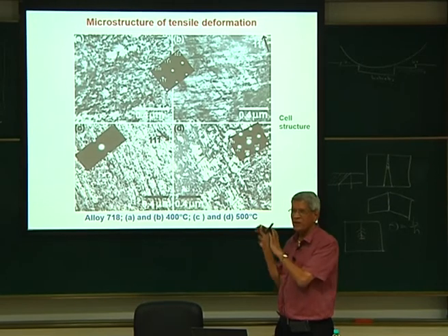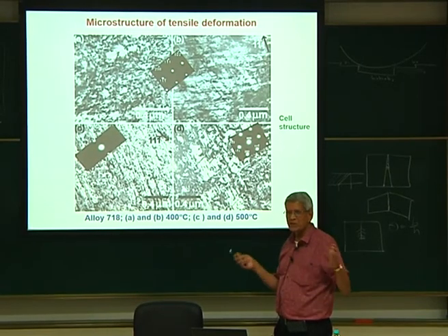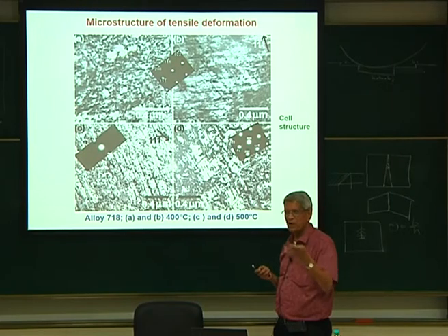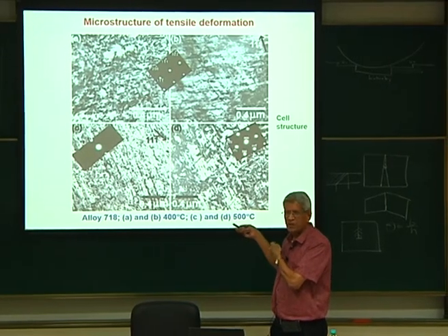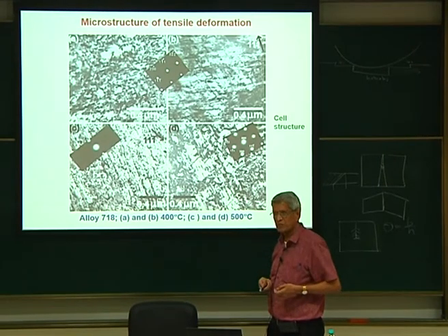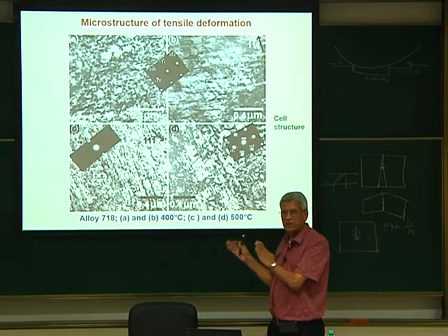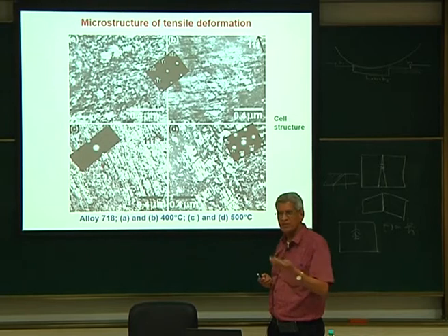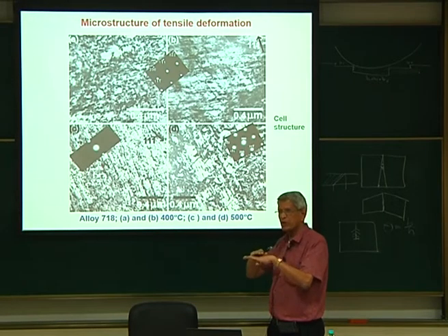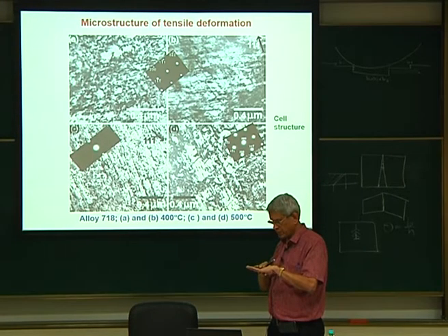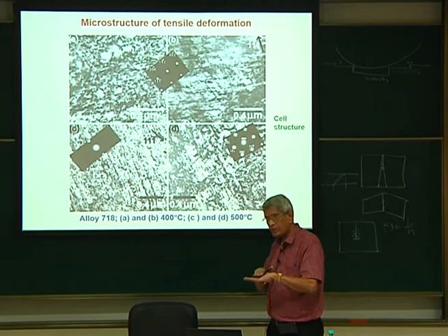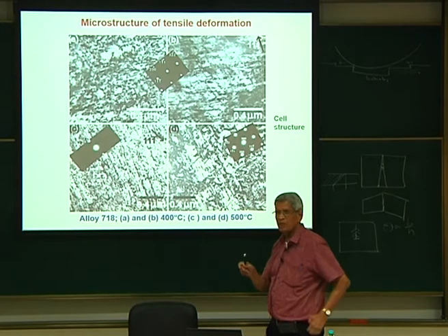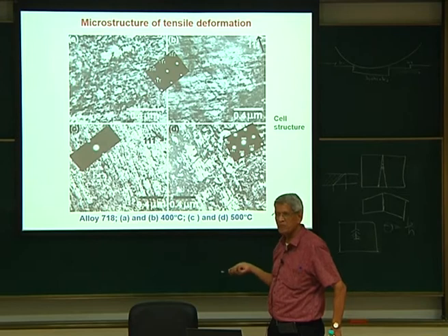If you do a tensile deformation, we will talk about that now, after just showing what the types are. But if you look at it, unless you do a careful analysis, you will not be able to find out what all these dislocations are, because there is also a set of dislocations present on the precipitate. They are arranged in a regular periodic way. One has to analyze it to find out what those dislocations are, for which one should know what the crystal structure is, and how it is oriented with respect to the other region. If you remember, we have seen earlier that if there is a slight misorientation between two crystals, then Moiré fringe contrast can come. So we have to identify that the fringes of the various types which we see are the dislocations.